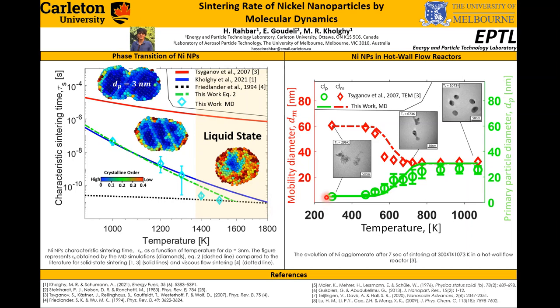The model shows that the average mobility diameter of agglomerate is rather constant up to around 500 Kelvin and steeply decreases to 35 nanometer as we increase the temperatures. For about 773 Kelvin, the agglomerates sinter into compact spherical structure and their mobility diameter asymptotically decreases to 32 nanometer, implying that nanoparticles are fully sintered. So we can see the spherical structure of nickel agglomerates.